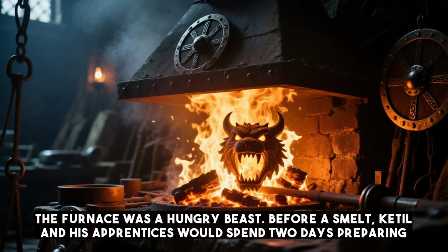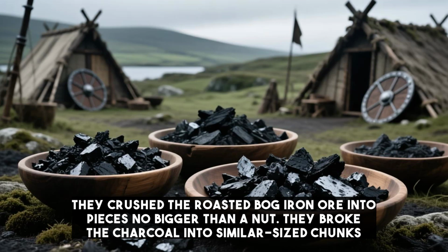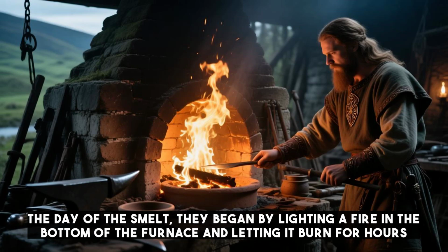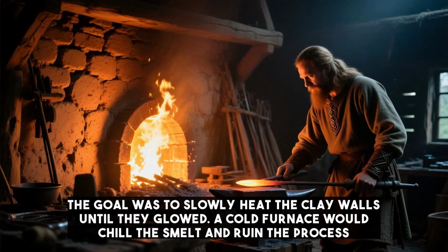The furnace was a hungry beast. Before a smelt, Ketil and his apprentices would spend 2 days preparing. They crushed the roasted bog iron ore into pieces no bigger than a nut. They broke the charcoal into similar-sized chunks. The day of the smelt, they began by lighting a fire in the bottom of the furnace and letting it burn for hours. The goal was to slowly heat the clay walls until they glowed. A cold furnace would chill the smelt and ruin the process.